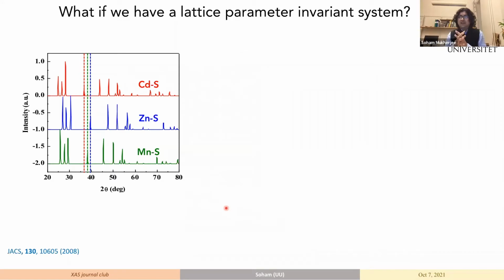So first of all, it could be that zinc and cadmium are of very different ionic sizes, and there's a huge lattice parameter variation. So it could be that the bond distances are not being able to catch up with the change of lattice parameter variation. So we move to a lattice parameter invariant system. And how do we do that? It is to follow that,